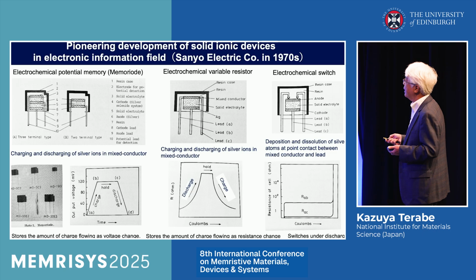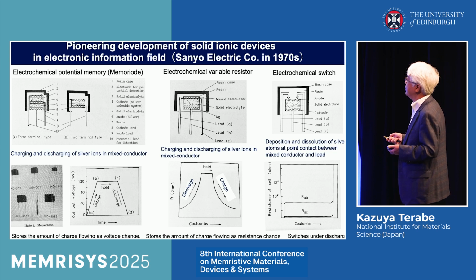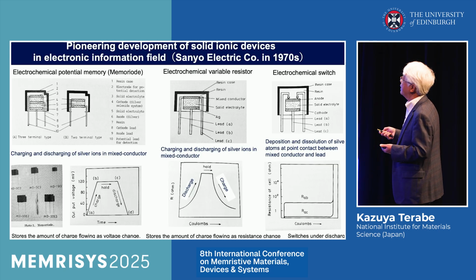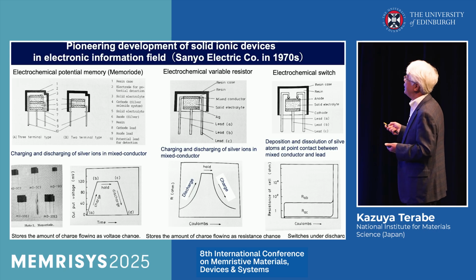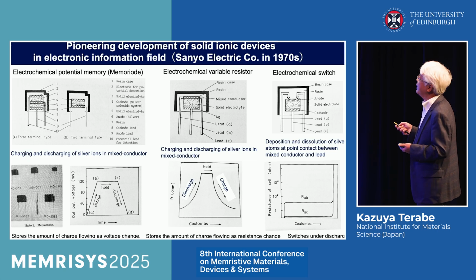This shows the resistance change during charging, discharging and charging. If the silver ion concentration increases, the resistance increases and holds, and when the polarity is changed, the silver ions are inserted into the mixed conductor and the resistance changes. This behavior is very similar to that of today's synapse devices.